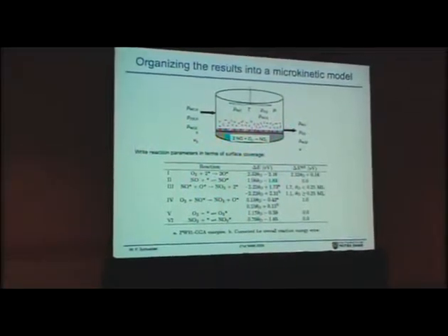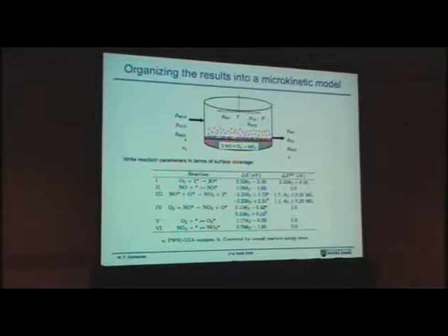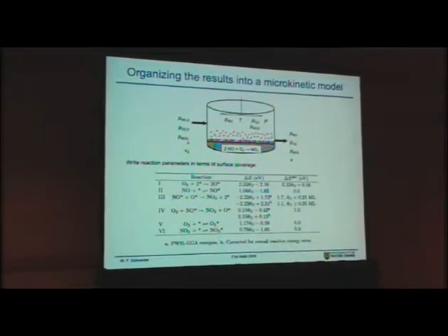The reason for that is that the standard DFT models, I mean the GGAs, grossly exaggerate the exothermicity of the NO to NO2 reaction. The GGA says that the equilibrium lies to products far more than it really does, and that makes lots and lots of problems when you try to model this kinetically. So we have to put an empirical correction into the model to fix that, so that we get the right equilibrium behavior and we get realistic coverages at the conditions in which the components exist.